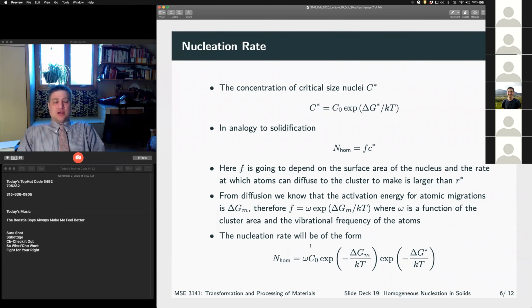So if we think about what goes into the nucleation rate, right? Our concentration of critical size nuclei looks exactly the same as it did before, right? What I want to know is how many nuclei of radius size R star. Well, I need to just plug in my Gibbs free energy here, delta G star. This is the number of potential clusters that I have, right? And we have our Boltzmann statistics. And then in an analogy to solidification, if we take the number of attempts times the number of clusters, we get our nucleation rate. Okay.